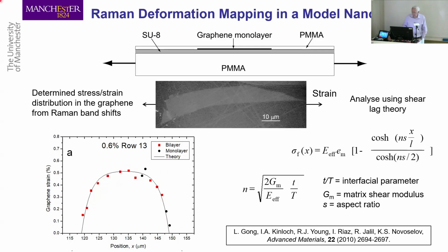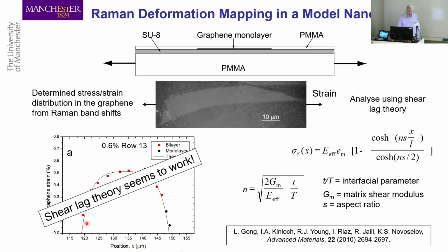And people who know about composite mechanics would immediately say, well, that looks like what you get if you put a fiber in a composite. And you can use this theory called shear lag theory, which tells you how the stress varies with length along an embedded fiber. And it's pretty well the same mechanics from an embedded graphene flake. And the solid line here is the theoretical line. So it tells us immediately that although this material is 1 atom thick, shear lag theory and continuum mechanics seems to work really well. And that is something we'll use later on in our analysis.